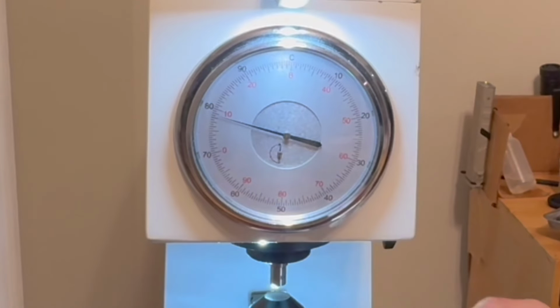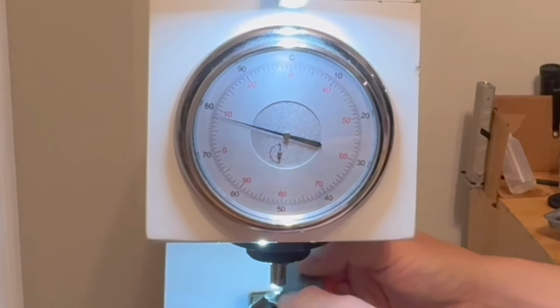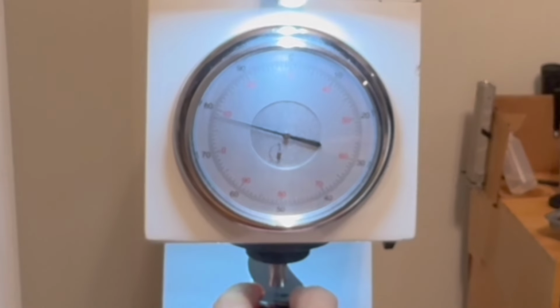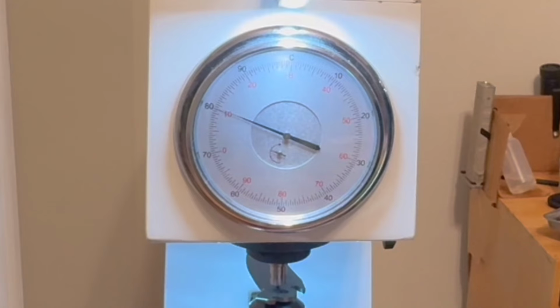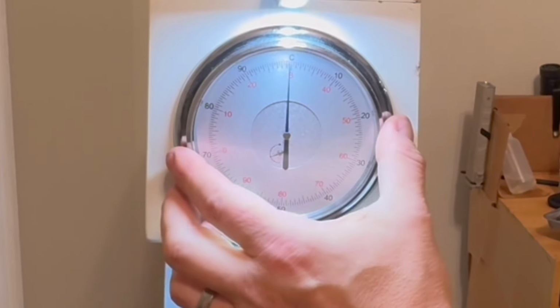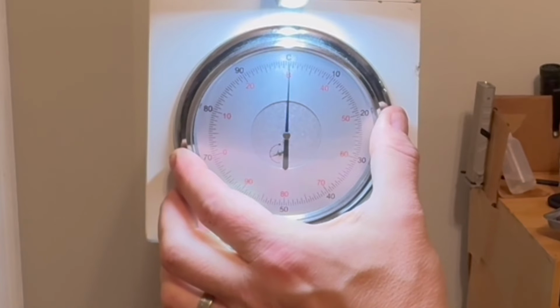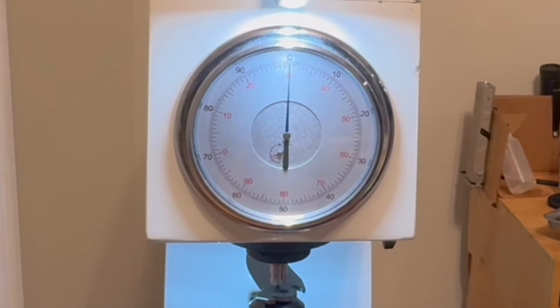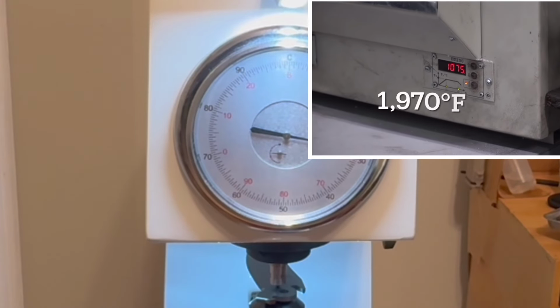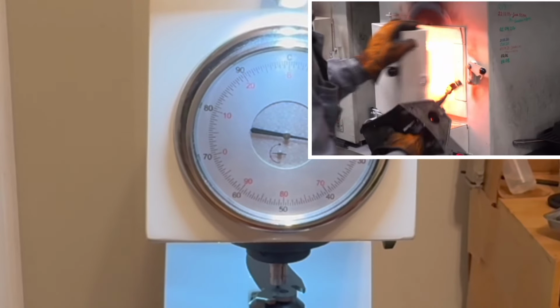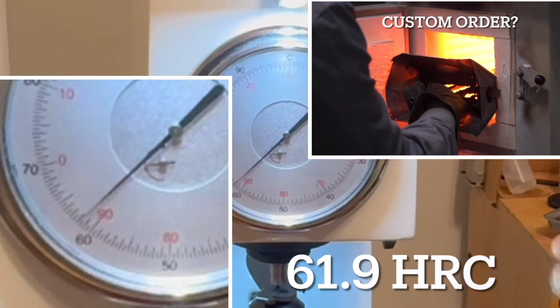Here it is. I'm putting the bare side up, and I'm going to test near the tang or back of the blade, so it's not visible when the knife is reassembled. There is a very good, very long video of the tour of Shirogorov's factory where you can see that they are applying heat treat to very small batches. We are talking 8 to 10 blades at one time. And this one comes up at 61.9 HRC.